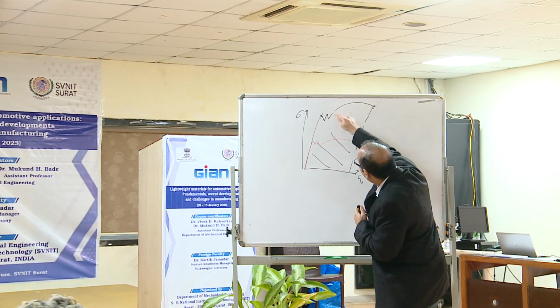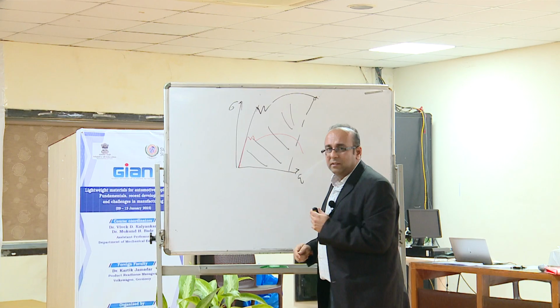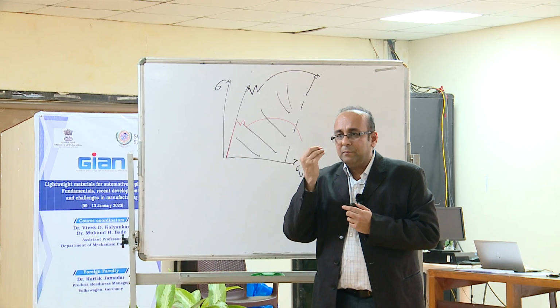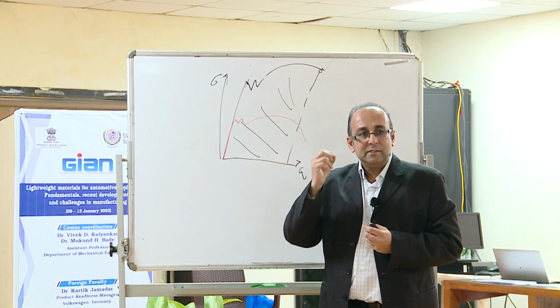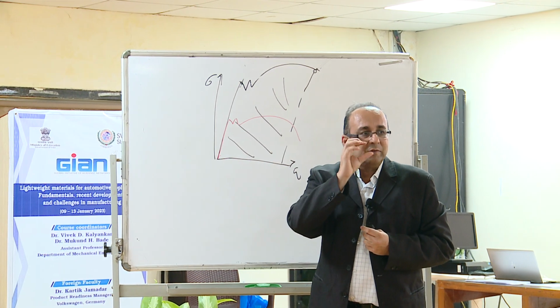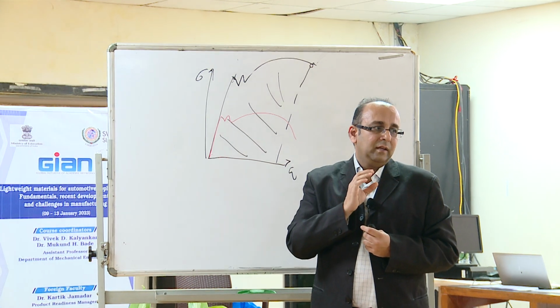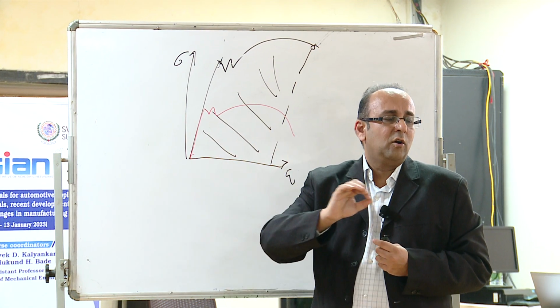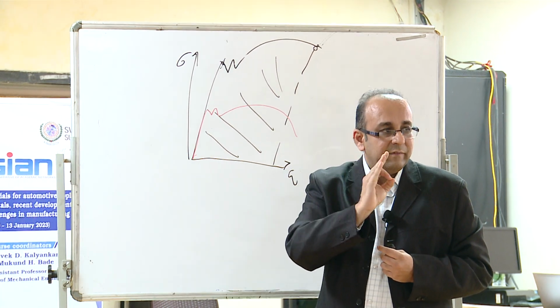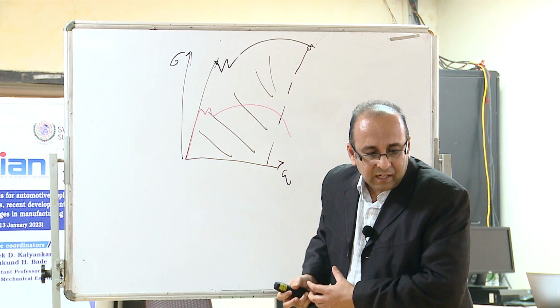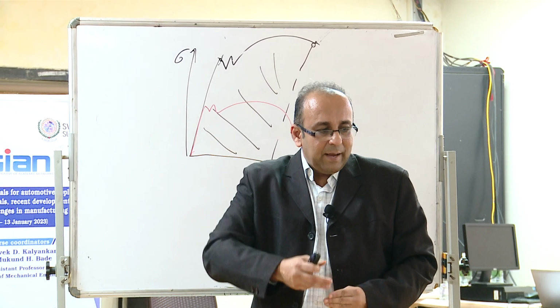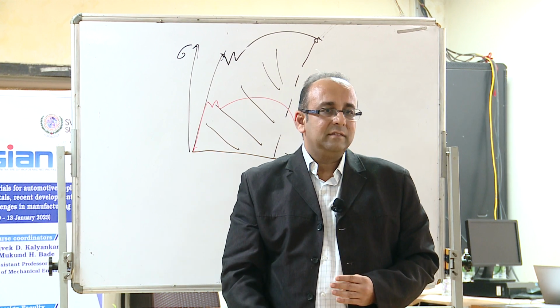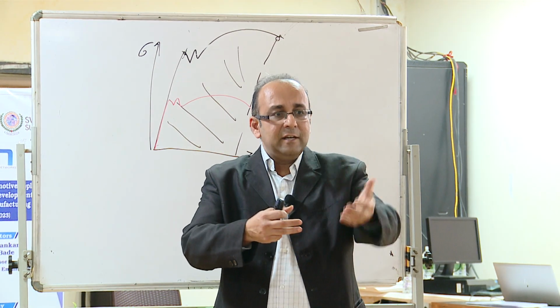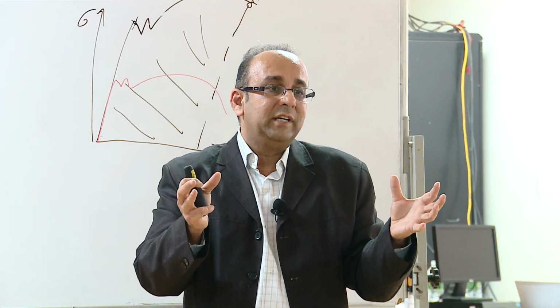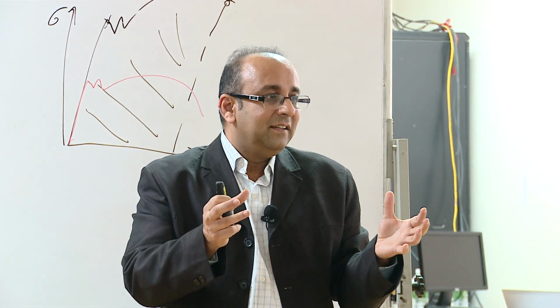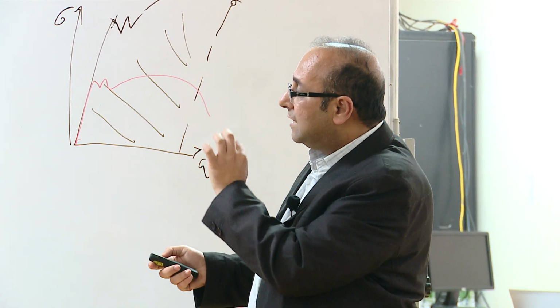You need some kind of plastic deformation area. Otherwise, it is like a glass. It's a brittle glass. It will break up. And that's why this Usibor is a very good material, because it has some kind of ductility which prevents the brittleness. Maybe not as high as stainless steel or something that has ferrite, but enough to prevent the brittleness. Otherwise, what will happen? Your car is going, it crashes, it absorbs the energy, and immediately it cracks. That is, the further energy will directly come to you, because the part has lost homogeneity. And that is the worst thing that can happen. So very important that this material has some kind of uniformity.